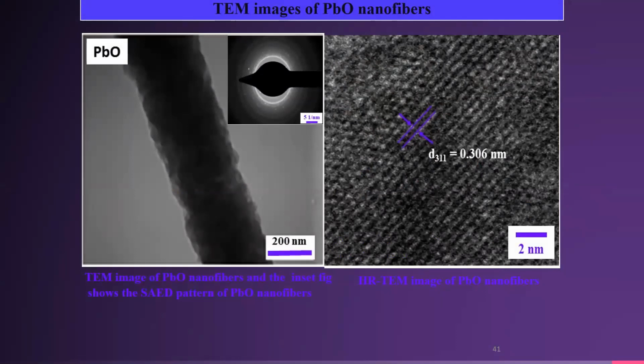These TEM images show the formation of one-dimensional beta PbO nanofibers with a diameter of 230 nanometers. We can see here the diameter falls under 230 nanometers, which is in good agreement with the SEM image and AFM result. The inset figure shows the beta PbO nanofibers. Results confirm the formation of polycrystalline nature. From the HR-TEM image, the interplanar lattice spacing of the 311 plane is found to be 0.306 nanometers, which is consistent with the orthorhombic phase of JCPDS data. Similarly, the TEM images of lithium manganese oxide nanofibers.